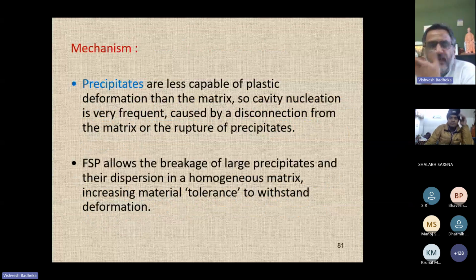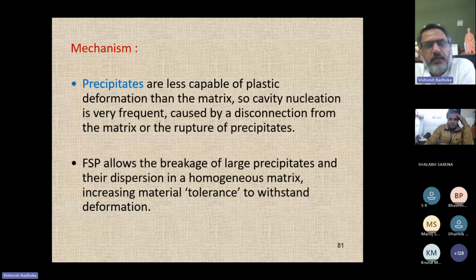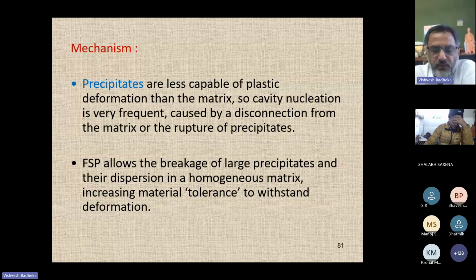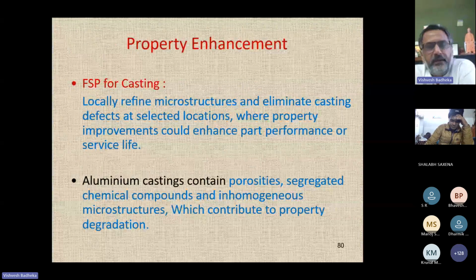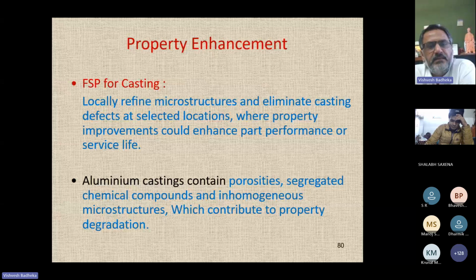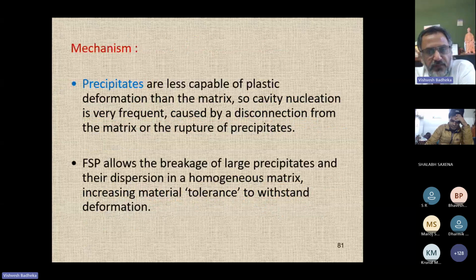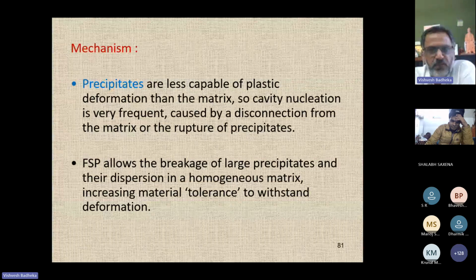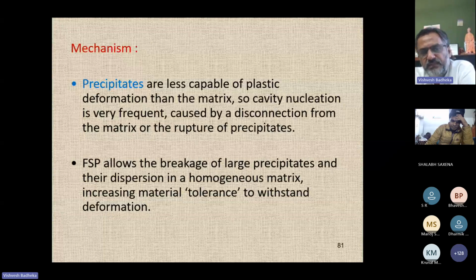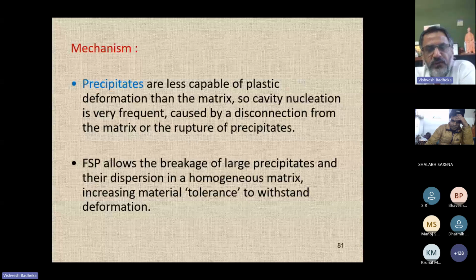So this is the mechanism I have already explained, but still, why are you getting improvement in the property? In FSP, the mechanism is that when you have precipitates, they are all intermetallics. Now these precipitates are not as capable of deforming as the matrix. The matrix is soft and precipitates are harder. So what will happen when you start deforming this material?